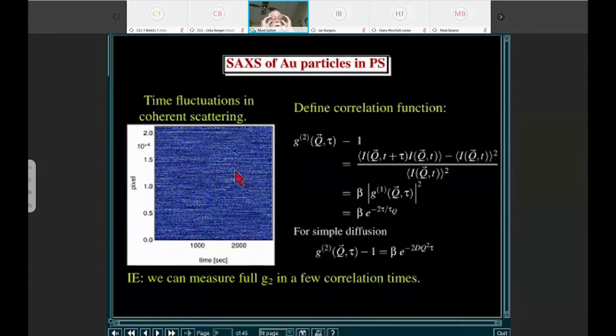So now, the question is, how do you analyze that? You can sort of see there's some time scale associated with this, but it's a very random process. What we're measuring here is the Brownian motion of polystyrene particles diffusing, or gold particles diffusing in a polymer of polystyrene. So this is basically the Brownian fluctuations of the small particles. Well, how do we analyze that?